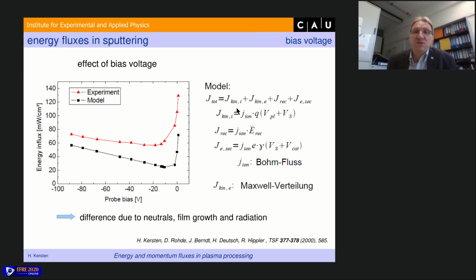And in our model, we took into consideration the kinetic energy of the ions, of the electrons, the recombination of the charge carriers, and also the secondary electrons. But you can see there's a difference between the model and the experiment. And this is due to the film growth. There's a growing film, and so you have condensation energy, and this is the difference. And the condensation energy is almost not influenced by the bias voltage, of course. This is not so influenced by the ions.